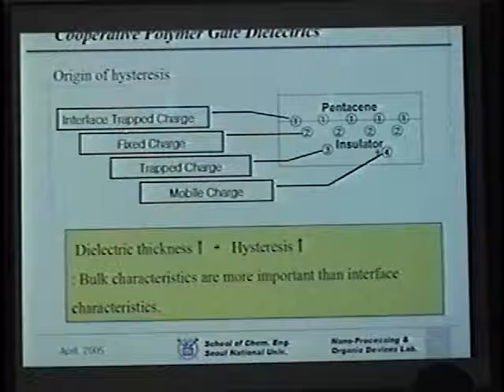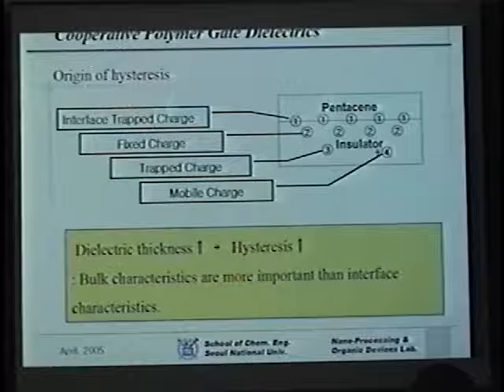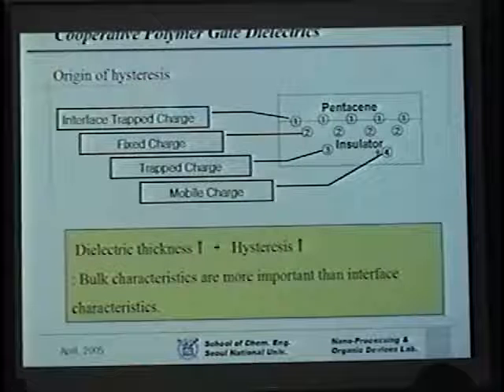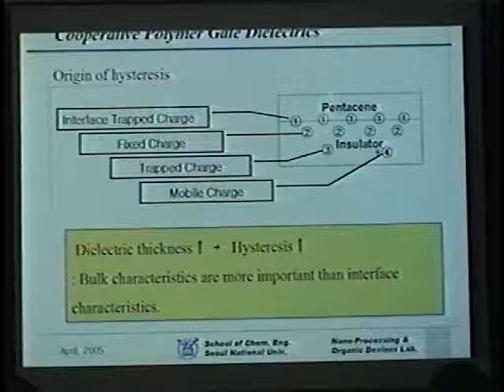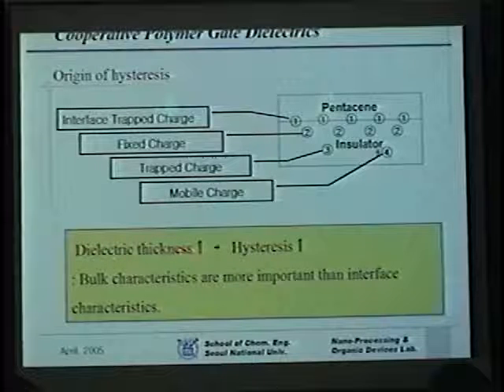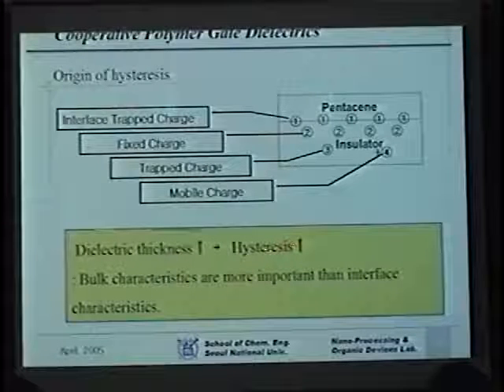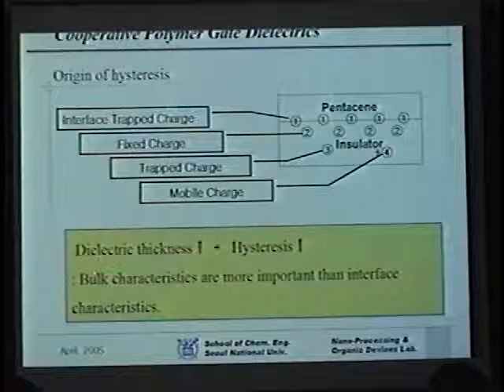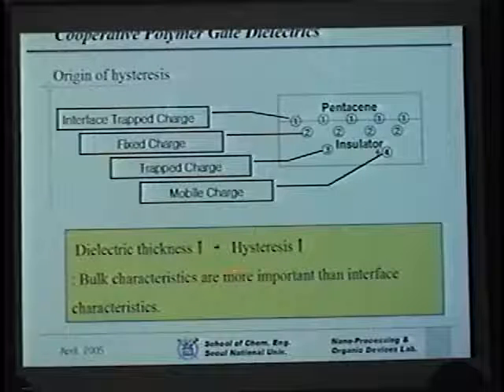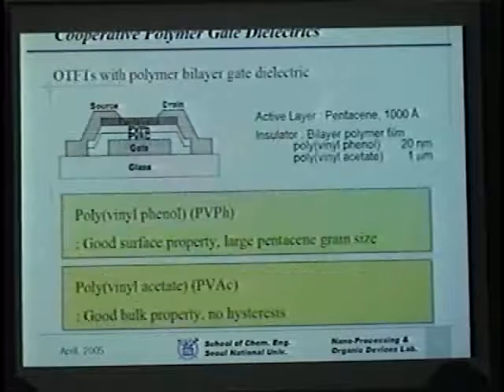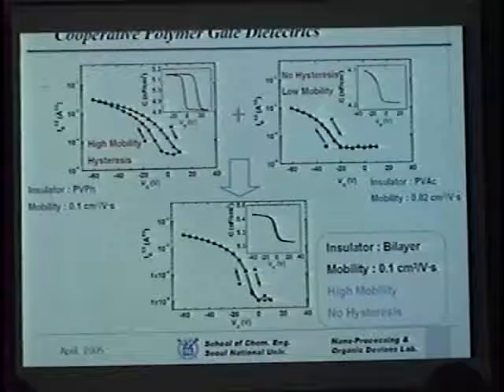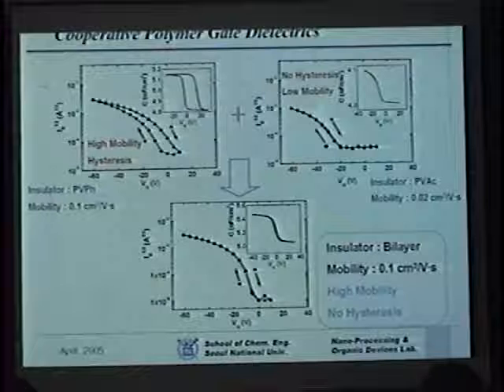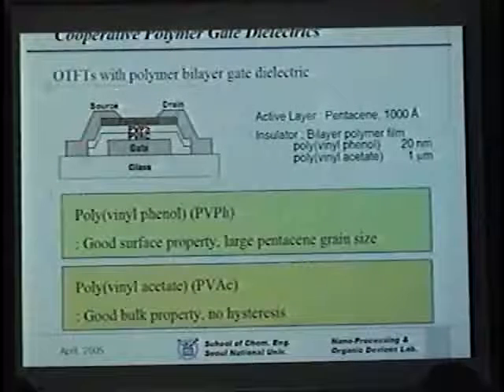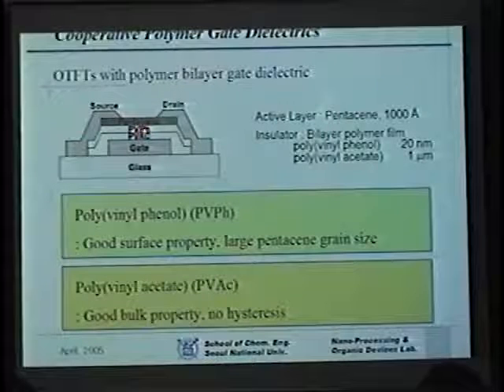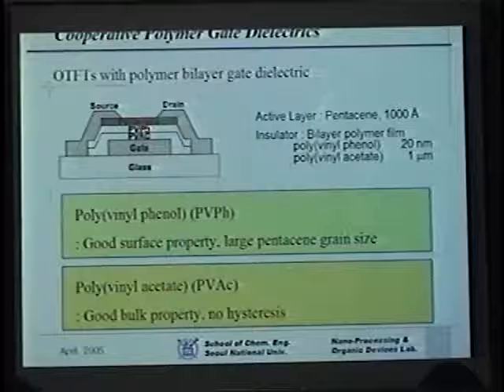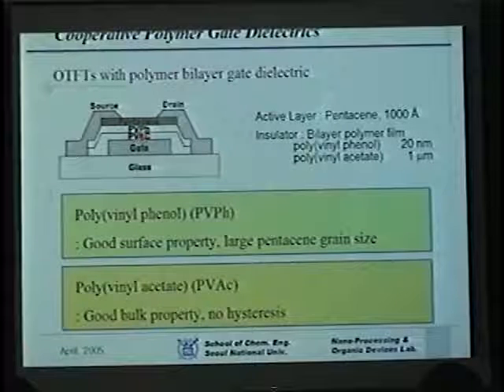In the literature, there are a lot of reasons given for this hysteresis behavior, that is, what the origin of this hysteresis is. But the fact of the matter is that whenever we increase the dielectric material thickness, the hysteresis also increases, which in turn indicates that perhaps this has to do with the bulk characteristics rather than the typical interface or surface characteristics. So what we did was use a bilayer, a very thin polyvinyl phenol and a very thick polyvinyl acetate film,